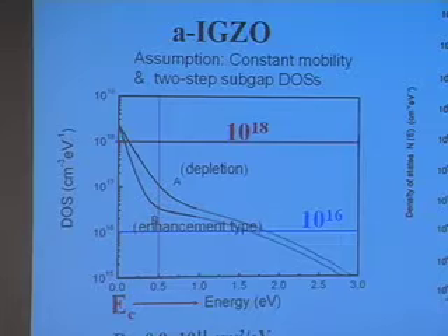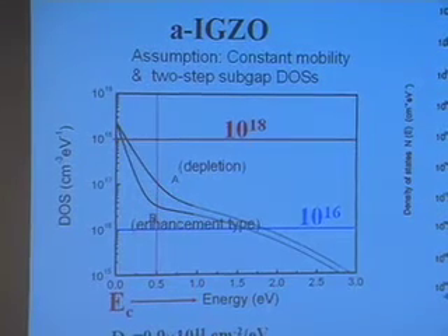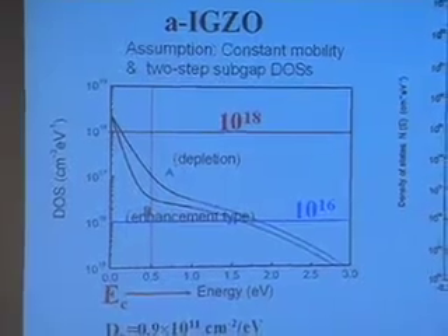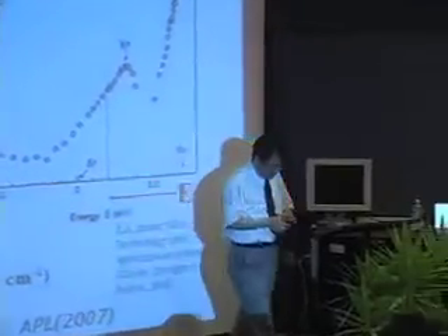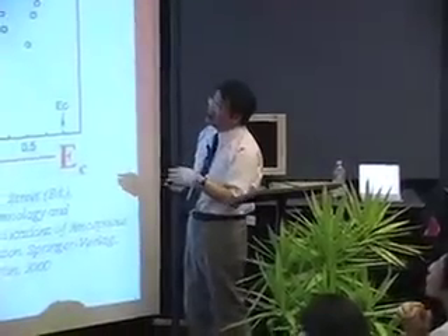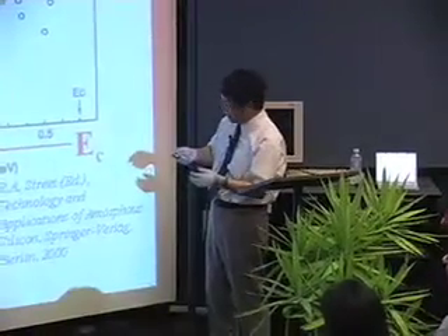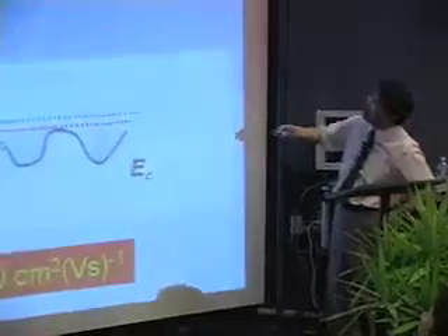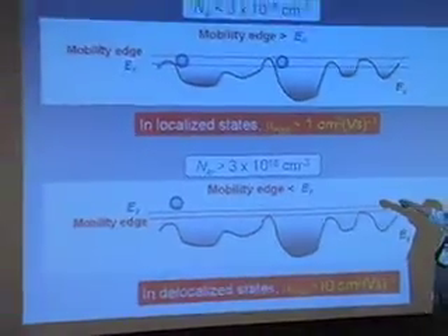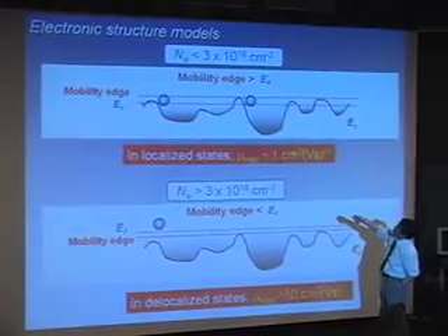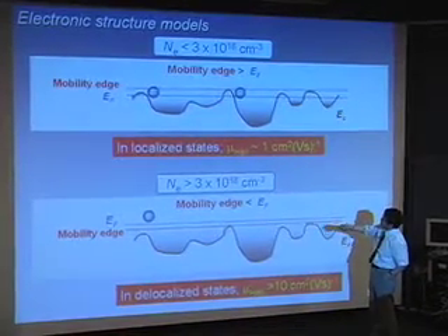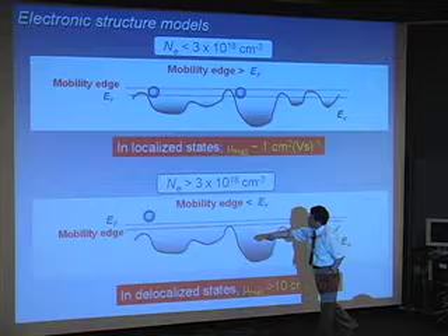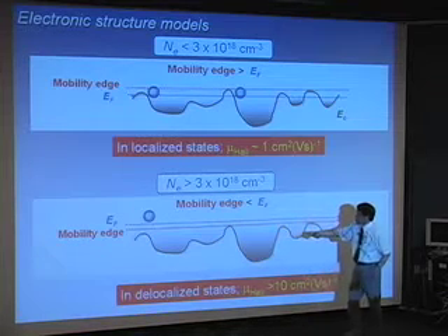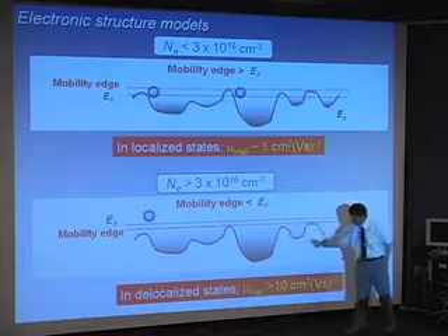If we can invent a method to compensate such defect states in amorphous silicon, we should achieve large mobility even for amorphous hydrogenated silicon. But anyway, amorphous oxide semiconductor exhibits very, very wonderful properties. This is a view graph: when the carrier concentration is low, it's impossible to overcome the potential well, but when the carrier concentration exceeds 3 times 10 to the 18th, carriers easily pass through, exceeding such barriers.